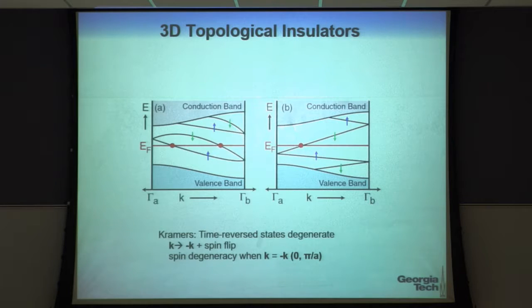Now, in 3 dimensions, if I have a 3-dimensional insulator, then things get slightly more complicated. There is a topological invariant again, and just think of it as if I have a 3-dimensional insulator, then the gap has surface states, okay, states that live only on the surface of the 3-dimensional insulator. They might look like this, where they have to be degenerate at k equals 0 because of Kramers degeneracy. This is a fundamental theorem that says time-reversed states have to be degenerate. In most non-magnetic materials, that means just that spin up and spin down are degenerate. Okay? But in a material that has spin-orbit interaction, I could have spin up and spin down being different energies. I haven't drawn minus k here, but if I look at minus k, I would see the mirror image of these bands and the spins would be inverted.